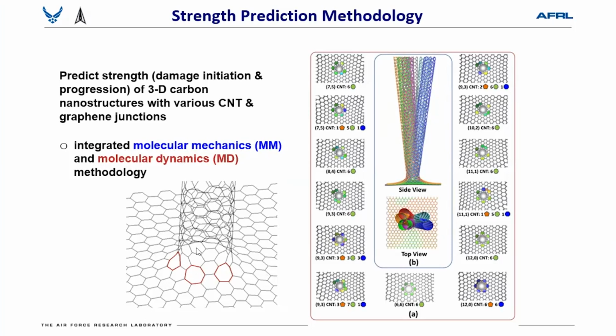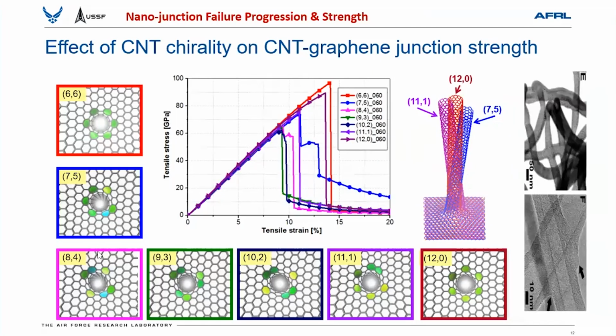Of course, carbon nanotubes have different chirality, and that gives a challenge, as I said before, in creating this kind of junction. We need 7-member rings to accommodate this kind of curvature. And depending on the chirality of the nanotube, the distribution of these 7-member rings around the circumference of the junction sometimes gets irregular, not uniformly distributed, unless it is armchair, 6-6, where these are equally distributed around the junction circumference. So with this, we did the calculation for strength prediction for different chirality junctions.